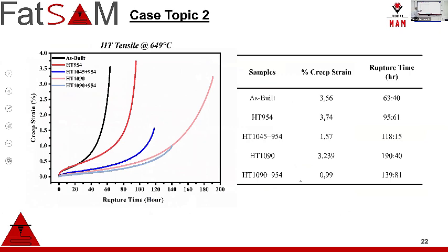As you can see, several properties which I like a lot: 1090 and 1090 plus 954. 954 is actually the solution temperature before aging. The issue is that after stress relief, or some people call this homogenization, what you would like to estimate? You would like to prolong its plastic deformation and life cycle under creep, or you would like to obtain less plastic deformation during creep. As I said before, most of the people prefer this one.